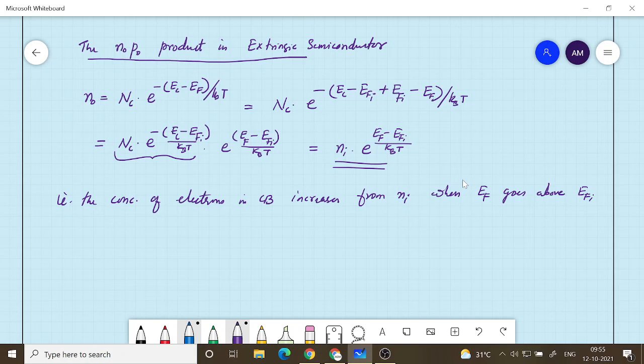But if EF is shifting above EFI, so EF is basically an imaginary energy level. It is not a real energy level where an electron can sit. It is a fictitious conceptual energy level where we say that the Fermi-Dirac distribution probability is equal to half. So that's an imaginary thing. As you add impurity, that energy level shifts upward, so that N0 can become high. So the way N0 can become larger than Ni is by changing the Fermi level above the intrinsic level. Same thing I can talk about with respect to holes also.